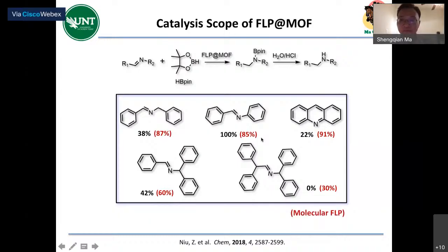But when we compare with the homogeneous FLP, molecular FLP in homogeneous system, they have very good conversion. You can see particularly this one, right? That means it's very interesting. That's a very interesting so-called steric selectivity. It's mainly because we increase the steric hindrance of this imine bond, and in homogeneous, there's no barrier. The FLP, the hydride, can be easily transferred to reduce this one. But that's not the case because of the MOF framework and the structure confinement. The migration of those hydrides is not easy. So that means they cannot easily access this imine bond.